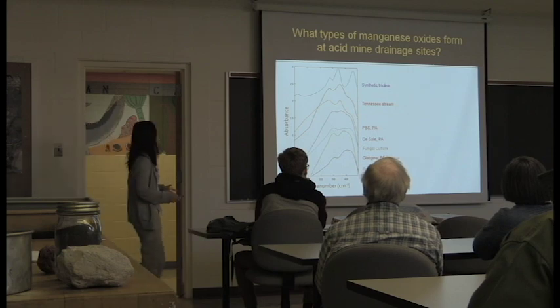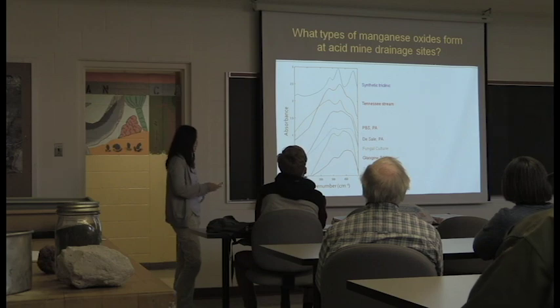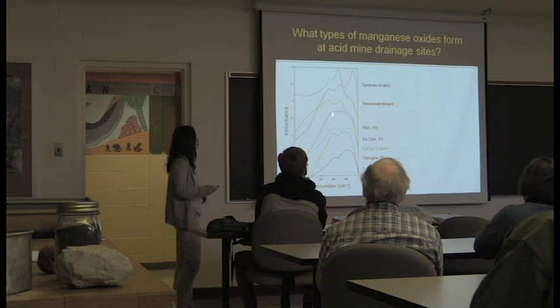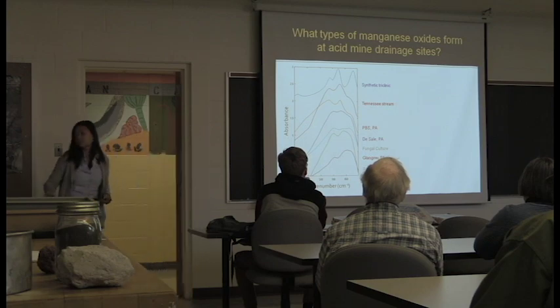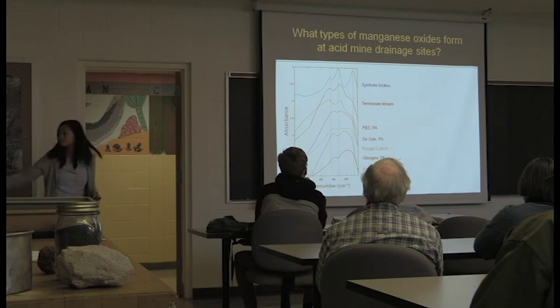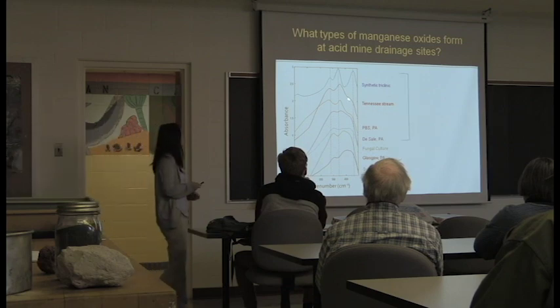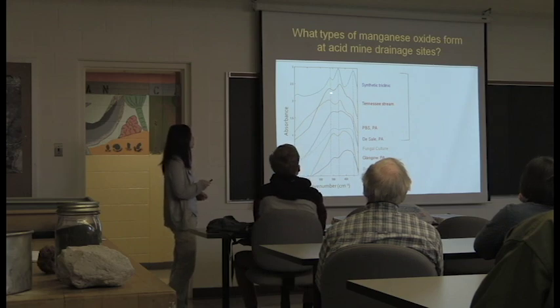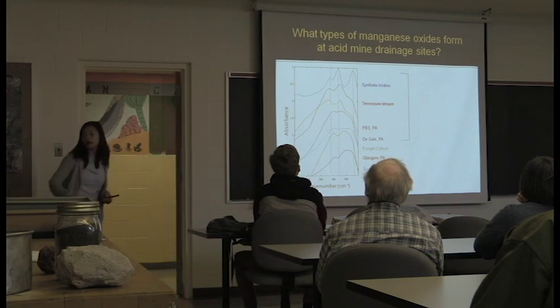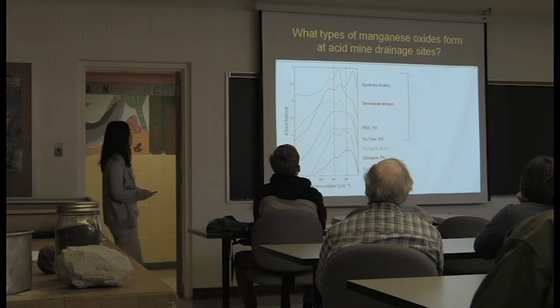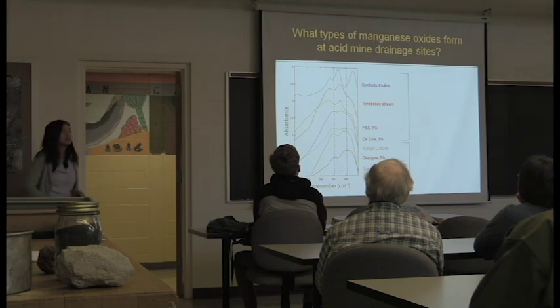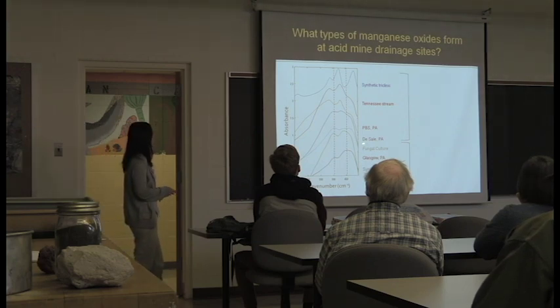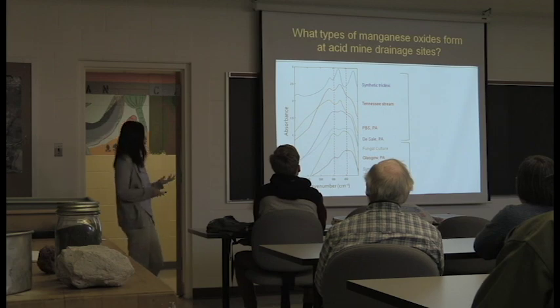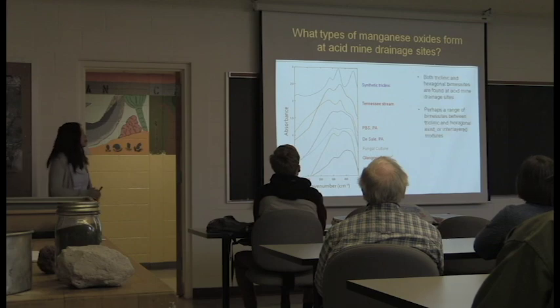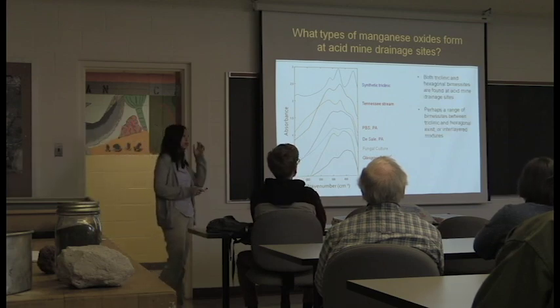So here I've zoomed in on the manganese oxygen bond distance region. And at the top, I have a synthetic triclinic birnessite for reference and a synthetic hexagonal birnessite at the bottom for reference. Everything else in between is a natural sample. And so if you look at your peaks for synthetic triclinic birnessite, you can see that some of these samples above have similar 3 peaks. So for example, this Tennessee stream sample, this PBS sample. If you look at the peaks for a synthetic hexagonal birnessite, you can see that some of the samples at the bottom also have these 2 defining peaks, especially this sample from Glasgow, Pennsylvania, which is the site that I was showing you.